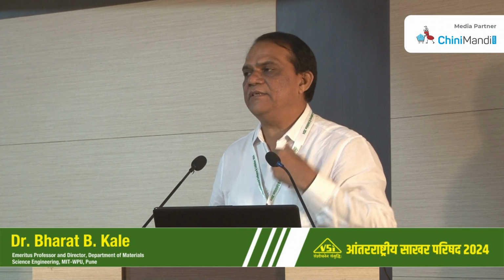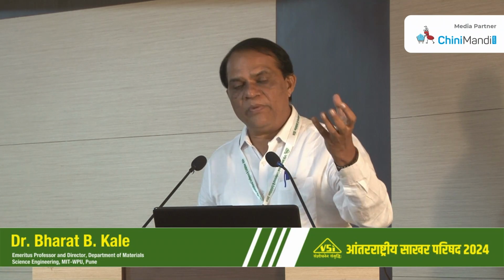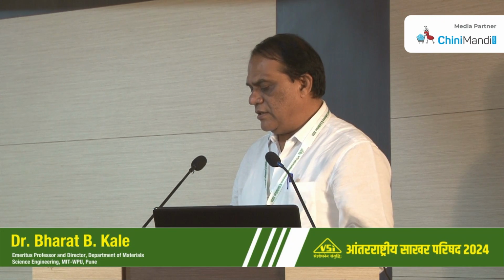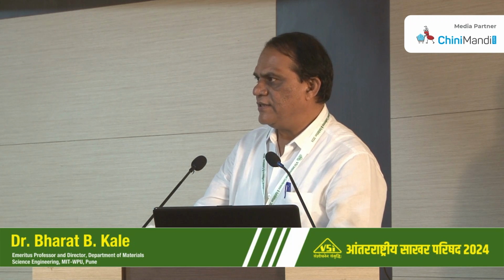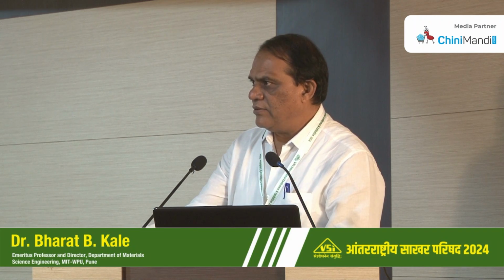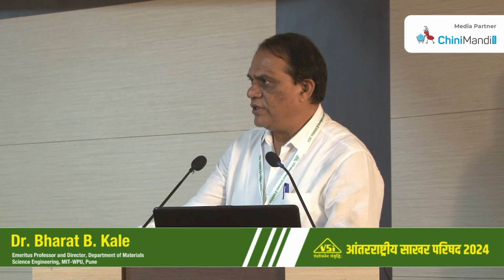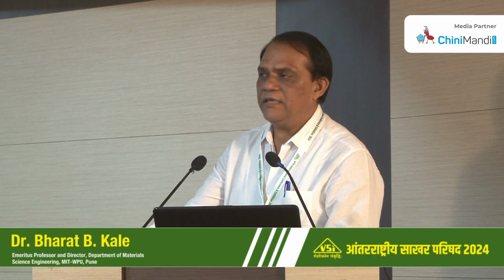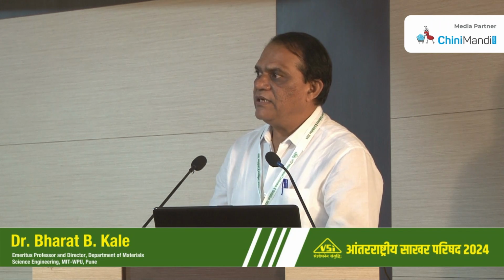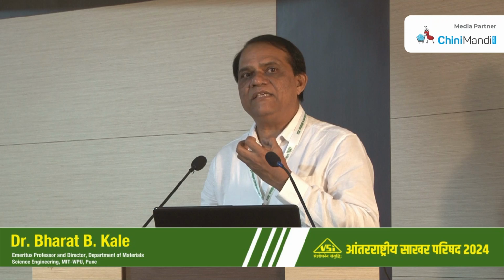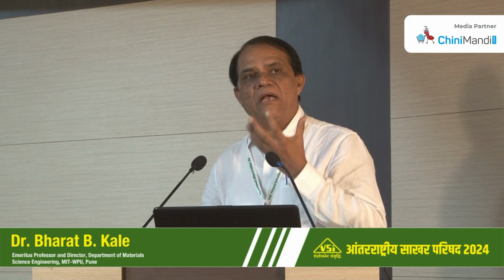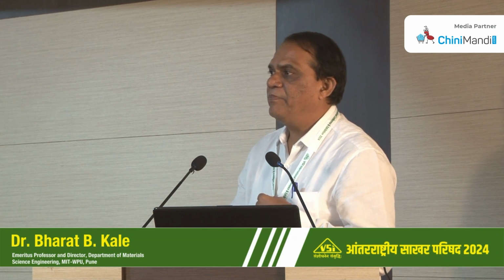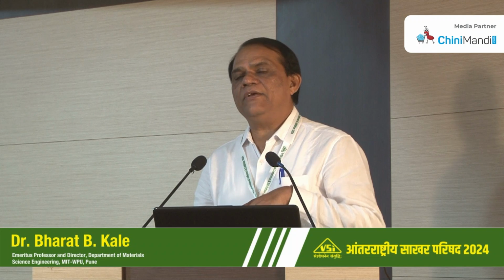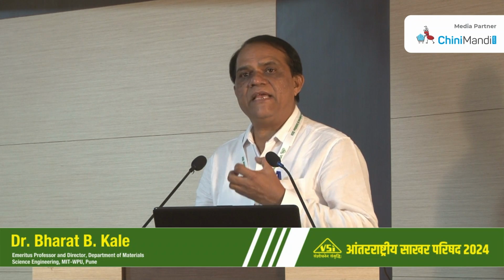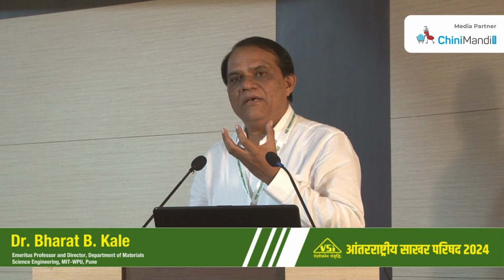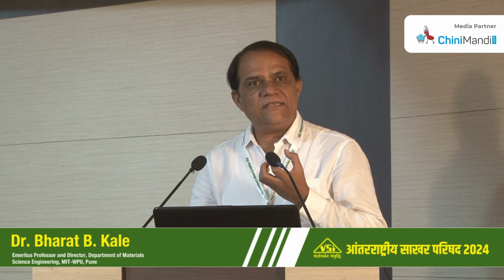The enhancement is much greater as compared to the bigger size. Here you can clearly see the 4 nanometer has 7,560, and even the 14 has 6,560. So it matters: when the quantum dot size is much smaller, we can get high hydrogen evolution. And the repeatability is the same, because recovery of the catalyst is very important.